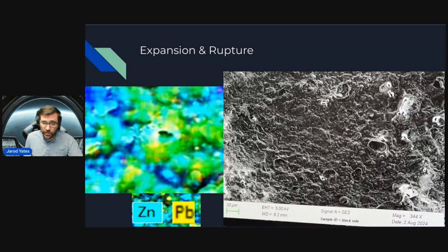In another scanning electron image that we have for the Falcon Space sample, you can see these things have ruptured all over the place. Most all of them have ruptured at a fairly significantly large size, anywhere from 20 to 40 microns. That's a really important piece of information: the smaller ones have not ruptured, but the larger ones have ruptured. That indicates a process is taking place. Also in this image, though it is somewhat difficult to see, there is a ring pattern of the ruptured spheres.